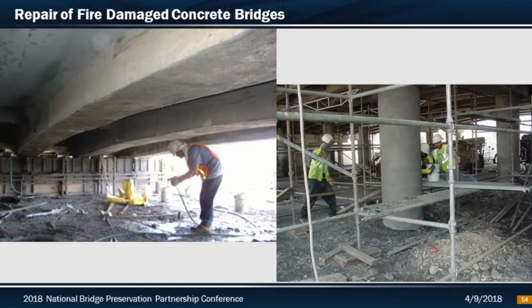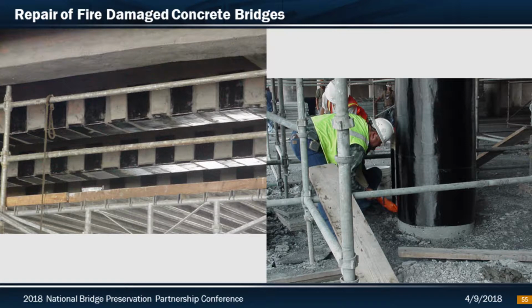Nice sandblast surface prep prior to your CFRP installation. In this situation, we just added one ply of longitudinal strips in the tension zone of the beam, and then the U-strips, again, wrapping up the beam web. This will enhance the structural integrity of the repair section, as well as reinforce the shotcrete cover concrete. 2 plies of horizontal CFRP were added on the columns, effectively adding confinement and strengthening.